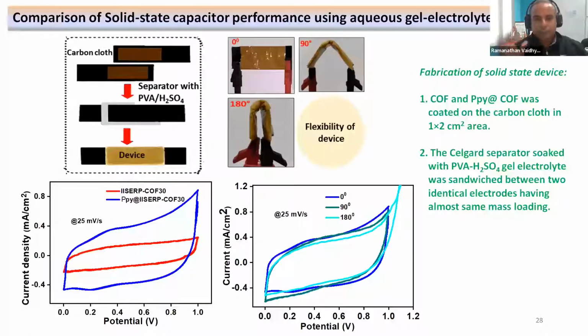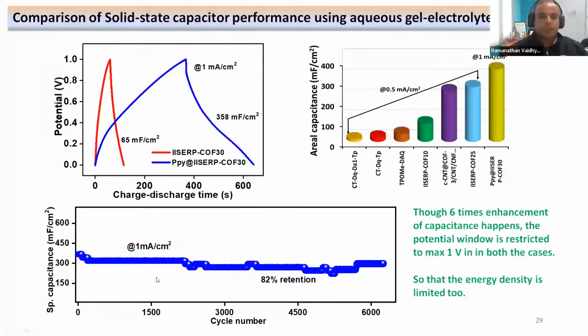But we need to show this in a 2-probe device, which is actually the working device, which we have made using this as a symmetrical capacitor. And you can see even upon flexing this device, still the cyclic voltammetry is completely intact, which shows the mechanical strength of this device. And the enhancement is seen also in the solid state device. So again, we compare the charge storage characteristics of the solid state device in the 2-probe measurement, and you can see the enhancement is very evidently seen, and the stability of the device is quite good.